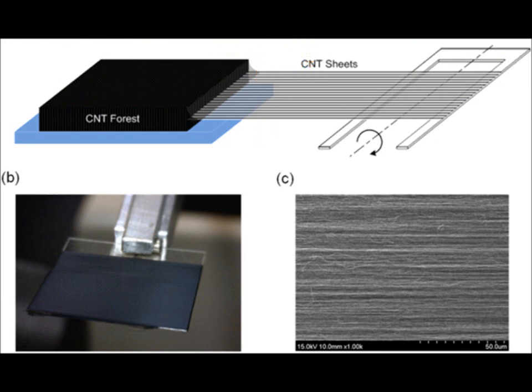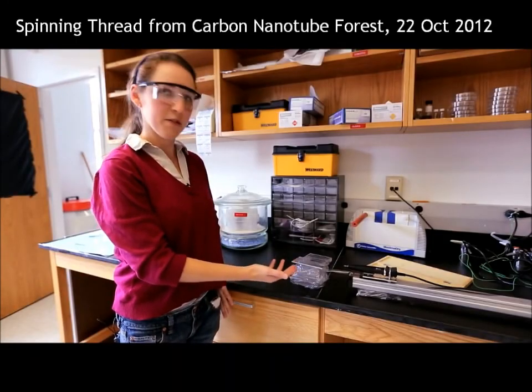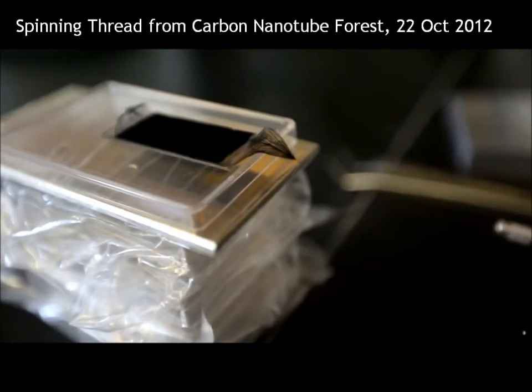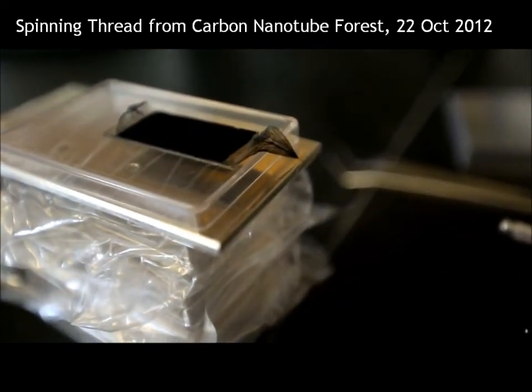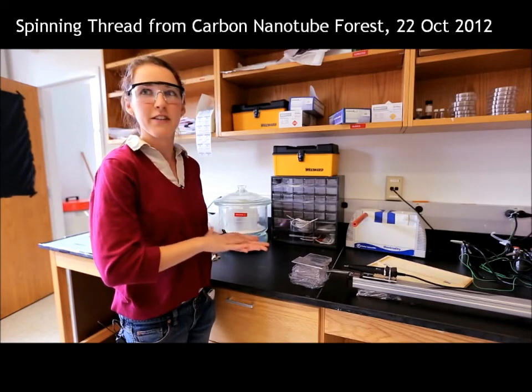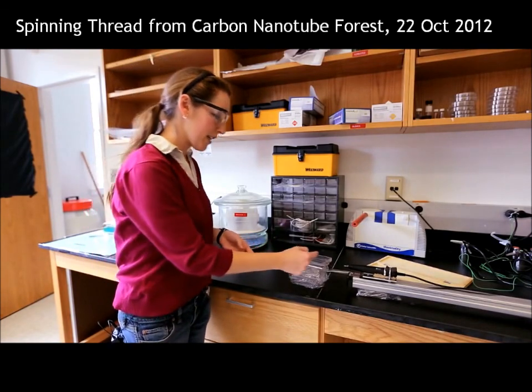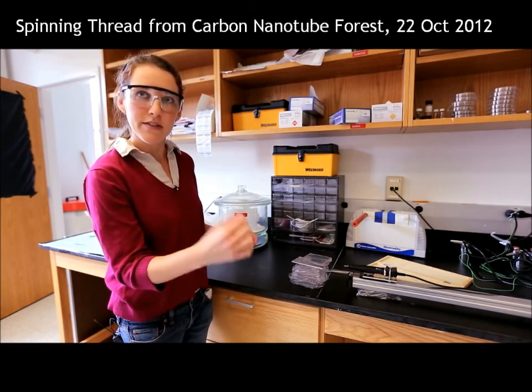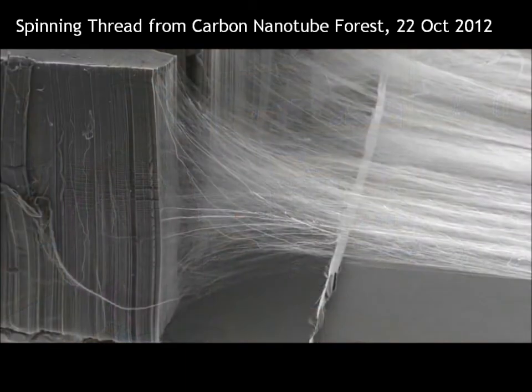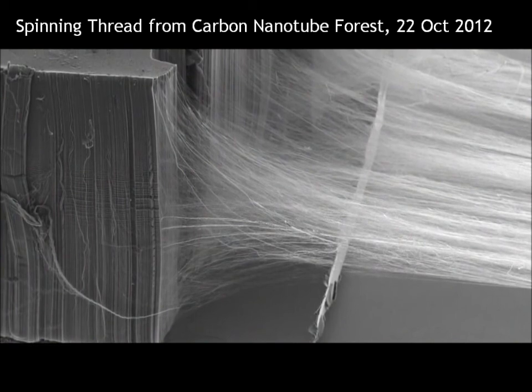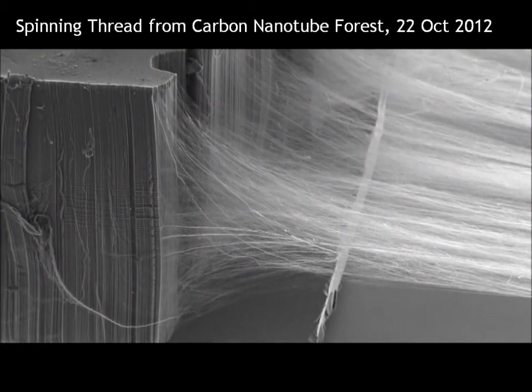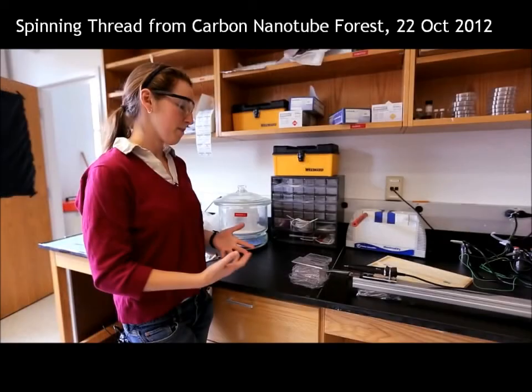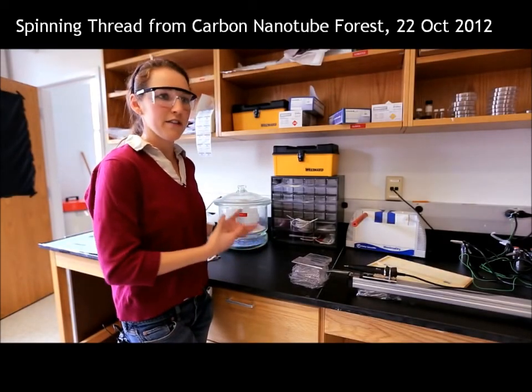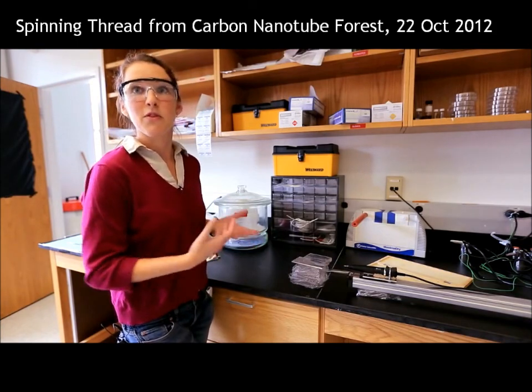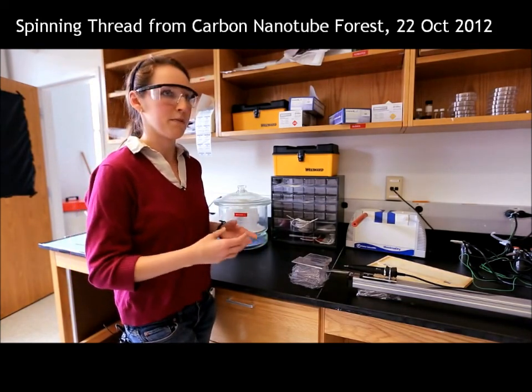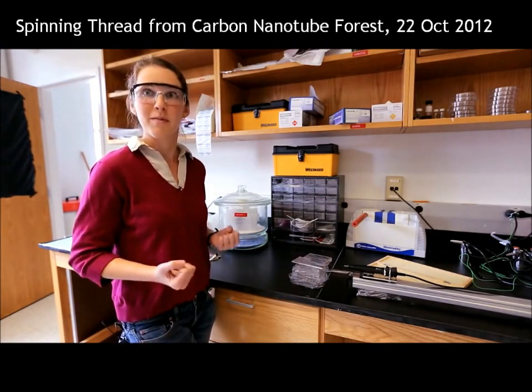So what we have here is actually a carbon nanotube forest. At a nanoscale they're very tiny, but when we grow enough of them together, we get a very high density of these carbon nanotubes. So it looks like a sort of fuzzy black mat. When we pull on the tip of one of these carbon nanotube bundles, we can pull out a web, and it almost looks like a spider web. As we twist that web, we can spin it, much like you'd spin yarn. It's just an example of carbon nanotubes. Although they are nanoscale, we're trying to develop ways to make them useful at the large scale. And this is one of the ways to make a cable or rope of a really strong material.